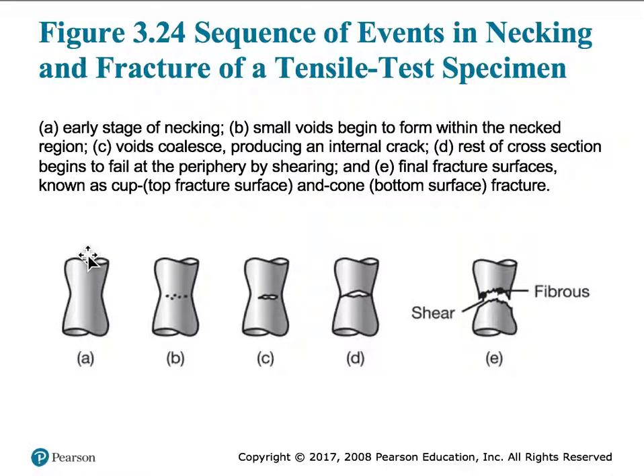When you are applying a tensile load on a ductile material, it will start elongating in the middle of the sample. When it starts elongating, the cross-sectional area starts reducing. It starts forming small voids, and those voids will start linking up. And then at this point, your sample is only held together in a couple of different places, which means that the area which is withstanding the load is no longer capable of taking the entire load, and beyond a certain limit that material will give way and break into two pieces. And this is typically called a cup and cone fracture. And when you put them together, you can see that they will both match with each other.